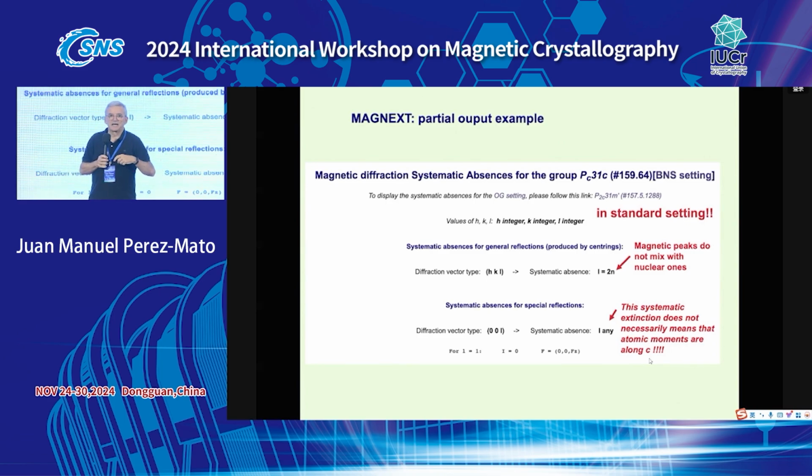But it can happen, and in fact, for any magnetic space group, if your magnetic atom is in a general position, the direction is completely arbitrary. The symmetry does not come from the symmetry of this spin. It comes from the relation of this spin with the other spins of the orbit, the other atoms. And this symmetry relation between different atoms will make the magnetic structure factor be along C, or be zero, maybe. Okay?